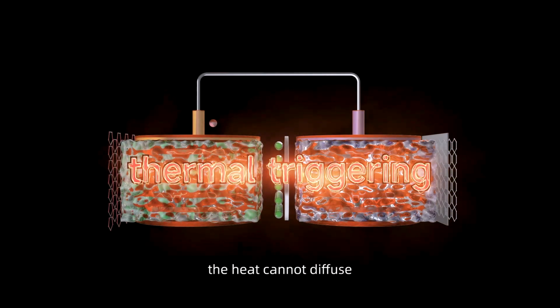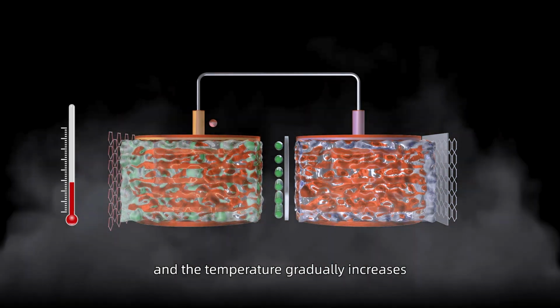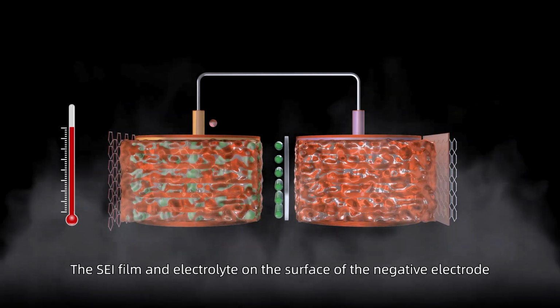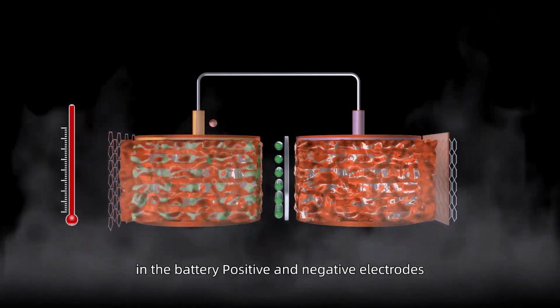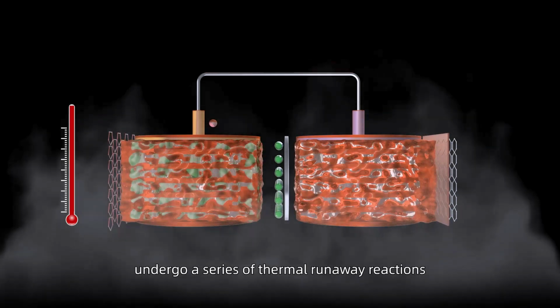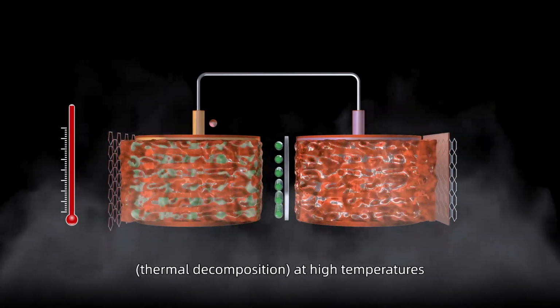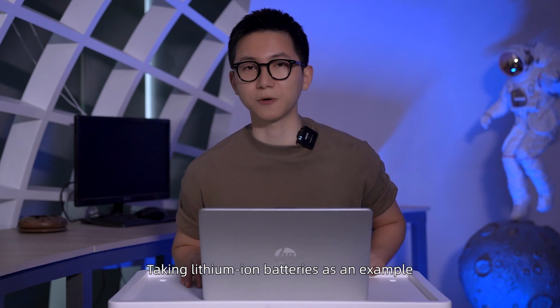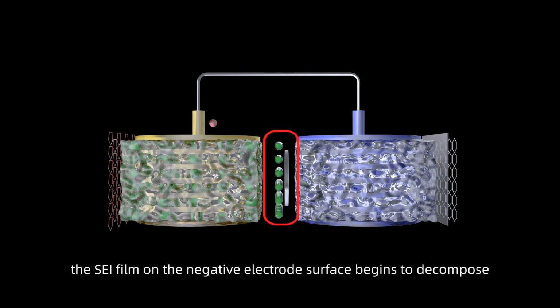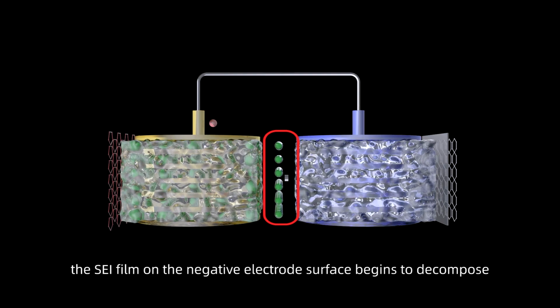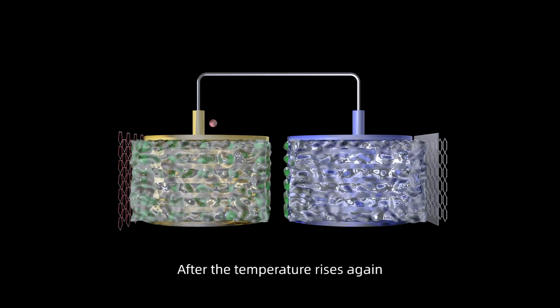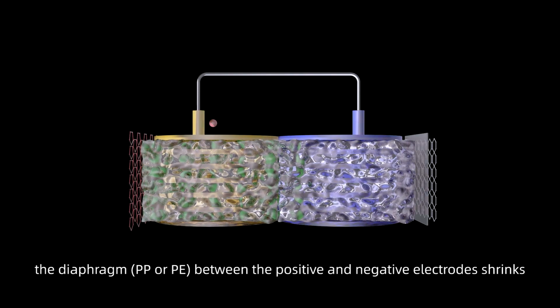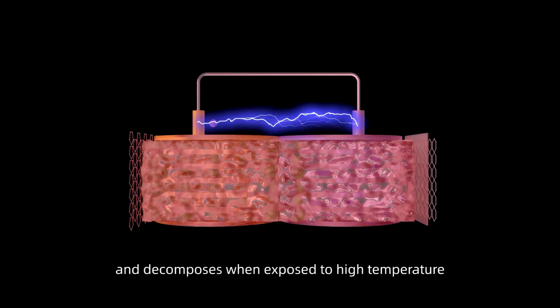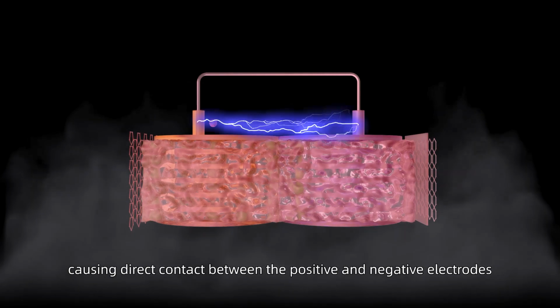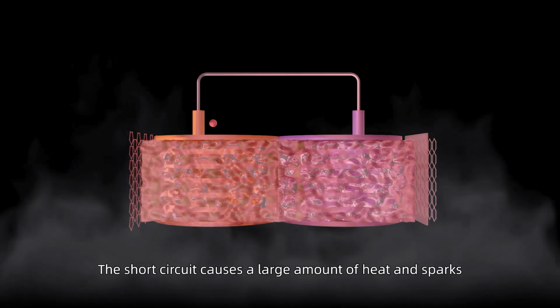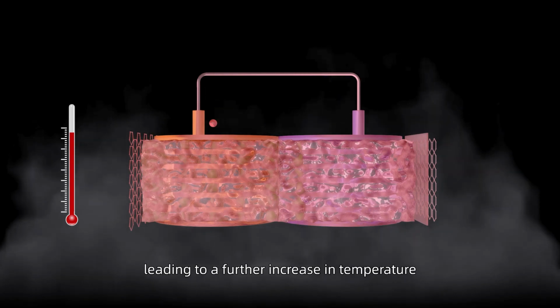In a short period of time, the heat cannot diffuse and the temperature gradually increases. The SEI film and electrolyte on the surface of the negative electrode undergo a series of thermal runaway reactions at high temperatures. Taking lithium-ion batteries as an example, when the temperature reaches 90 degrees, the SEI film on the negative electrode surface begins to decompose, and after the temperature rises again, the diaphragm between the positive and negative electrodes shrinks and decomposes when exposed to high temperature, causing direct contact between the positive and negative electrodes. The short circuit causes a large amount of heat and sparks, leading to a further increase in temperature.